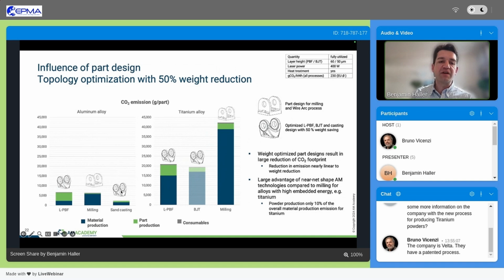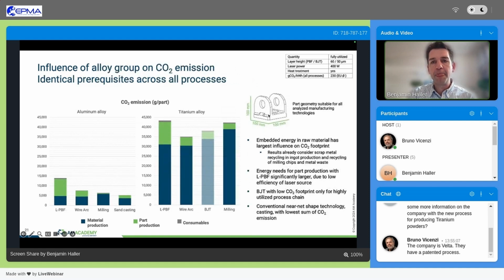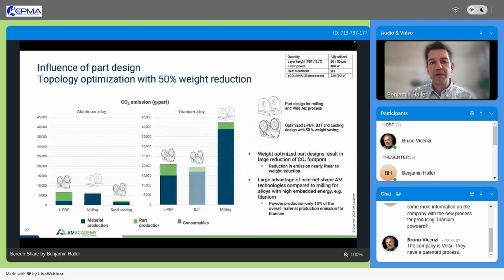Whereas sand casting in this example is even lower, because also here we can produce the optimized part. For titanium, where if you look back at the example we had higher CO2 impact for the LPBF part, we are now significantly lower, again because of the higher share of the raw material. So especially for titanium, it has a quite big impact that we use parts that have been designed for additive manufacturing. And this we will talk about again at a later stage.